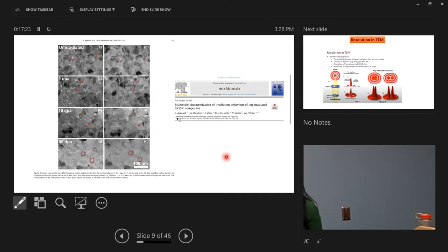So this was tested for high temperature reactors, or basically for ATF, accident tolerant fuel development. This was the material and we were testing it at very high doses. This was an experiment that we did. As I increase the dose from unirradiated to 1 dpa to 10 dpa to 50 dpa, what I see is that gradually the density of these carbon packets starts diminishing. And in the final one at 50 dpa, there is no carbon packet left. So this is one of the examples of the studies that we can do by changing the overfocus and underfocus.